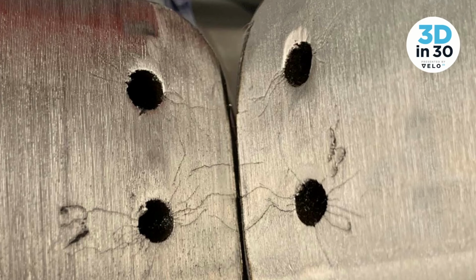What happens when you see this type of failure mode? So every tool, especially in the die casting world, eventually breaks. It sees 600 Celsius aluminum on one side. It sees cold water in the channel. Regardless, additively or not, that thermal gradient and that cycling back and forth every minute or two is massive. And so all those stresses continue to build up until eventually you get a crack form from the casting surface down to the water line, and the water line leaks. And you have to shut the machine off and replace the tool.